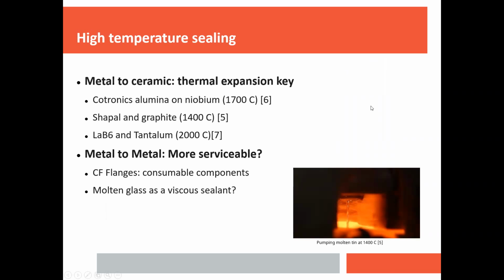And then the other thing for engineering purposes, high temperature metal sealing is critical. Most liquid metals that you might work with, maybe barring glassy alloys, are very, very low viscosity, lower than water even. So you need really good sealing at very high temperatures, which means you need things that have matched thermal expansion coefficients for the most part, or you need metal-to-metal interfaces. So there are three examples: alumina to niobium, Shapal, which is a ceramic from Japan, and graphite. Those are both machinable, so that's easy to work with. Cotronics alumina is castable, niobium is machinable. Lanthanum hexaboride is not really machinable, I would say, but that to tantalum makes a good interface up to even 2000 C, depending on your application.